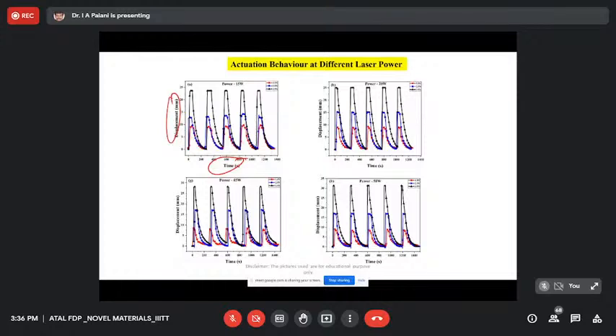So with 15 watt power, with a 1.5 Newton load, a displacement of up to 10 mm was achieved. Okay, slowly when we try to increase the power, the displacement was also getting increased. So the maximum displacement we could achieve is something around 30.